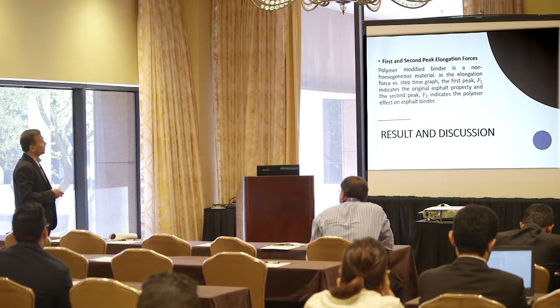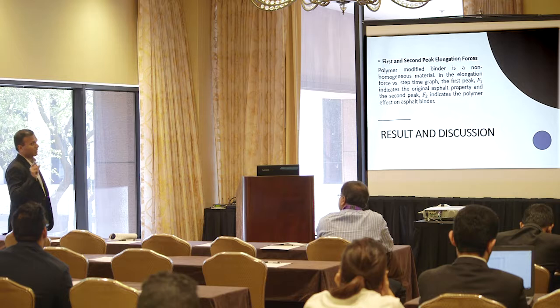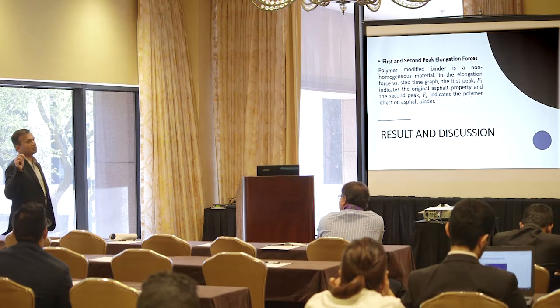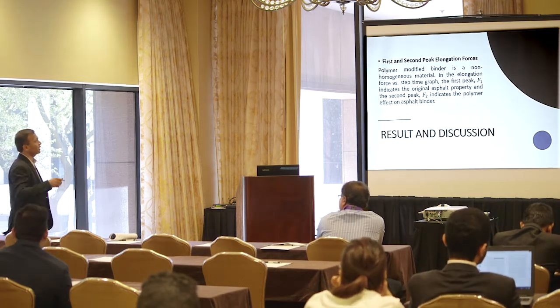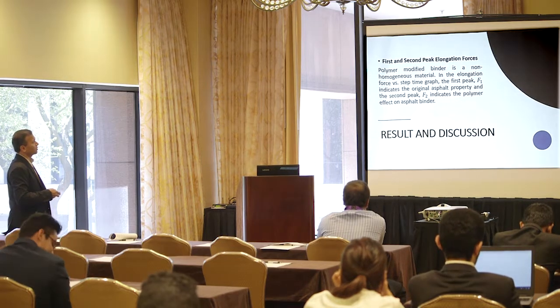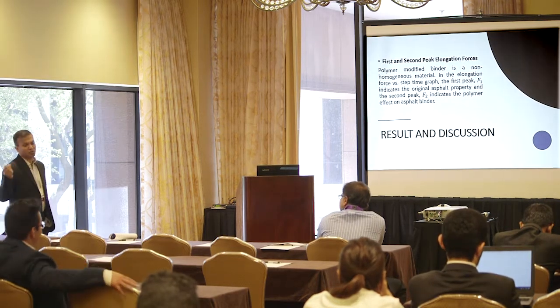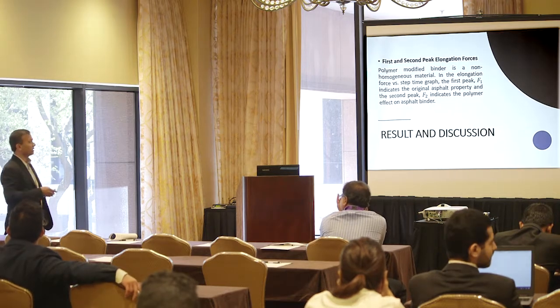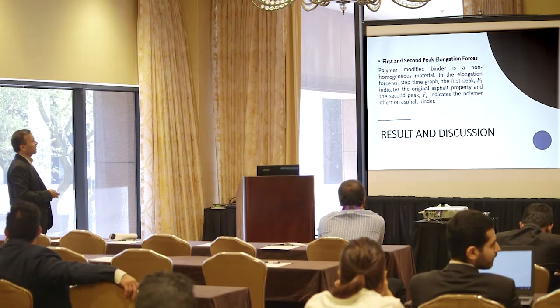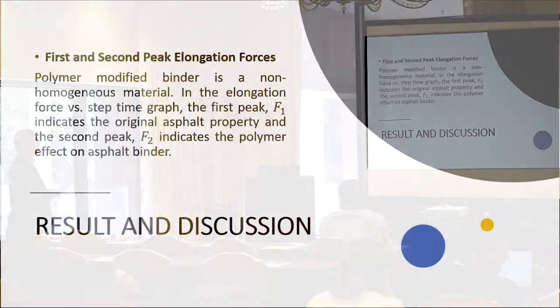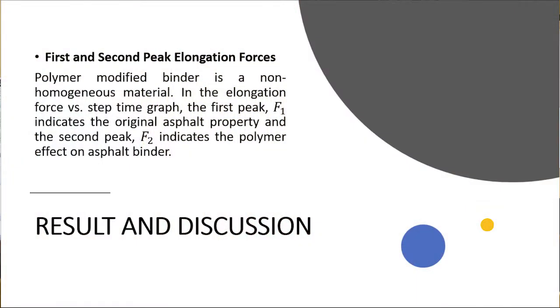Okay, so the first peak. Polymer modified binder is a non-homogeneous material. So when you say asphalt, it is asphalt binder and polymer. So two things are there. In the elongation force versus time graph, if you have not ever seen any force ductility test results, it has two peaks. One is the first, F1. When you first try to pull the material, the maximum force you see comes from the asphalt binder itself.